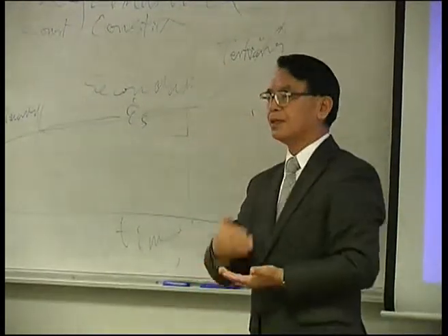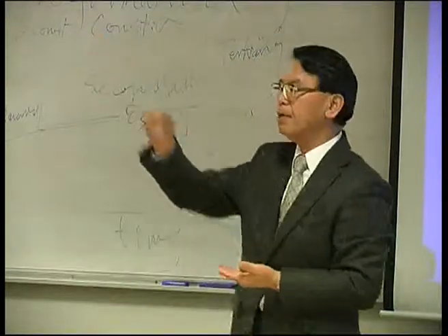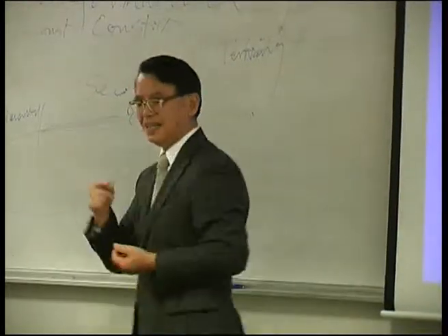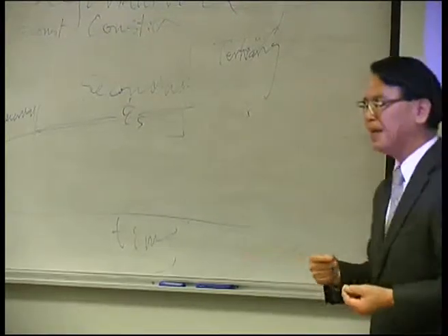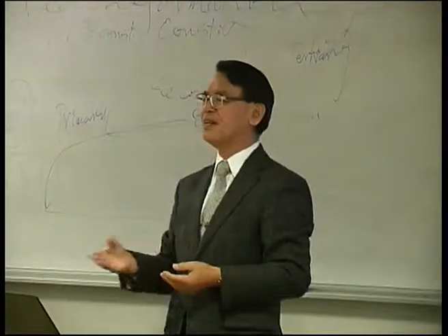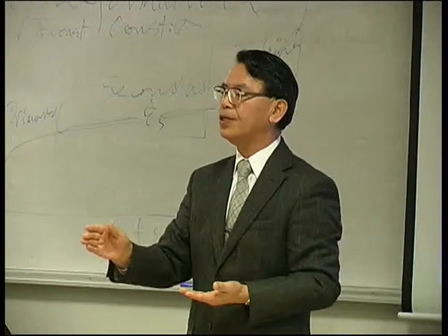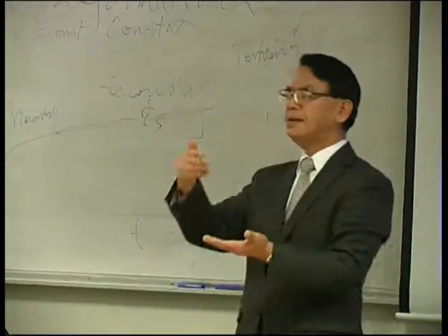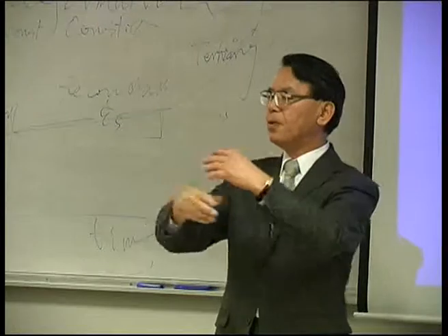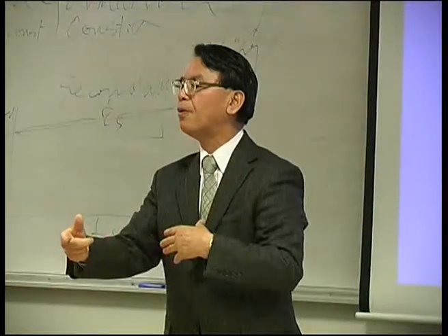Of course, deformation is due to dislocation motion, at low temperature, or at high temperature, diffusion-controlled dislocation motion. The first work was published in 1966, my first paper as part of my PhD thesis. I studied the mechanism of creep deformation in pure iron. In that case also, diffusion controlled the dislocation motion. But in ferromagnetic states, as I mentioned lastly, the domain wall exists and the dislocation has to interact with the domain wall.